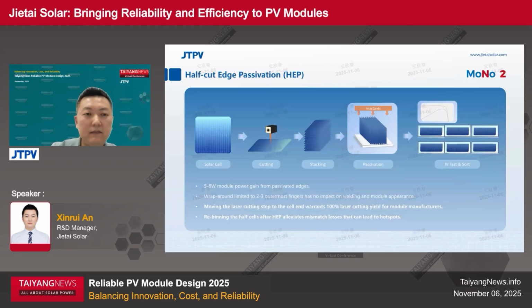And the other feature of Mono 2 cell, the half-cut edge passivation, HEP, not only enhances module power by 5 to 8 watts, but also contributes to more reliable modules. First, our wraparound is limited to the outermost 2 to 3 fingers, thus having no impact on welding or module aesthetics. And more importantly, moving the laser cutting step to the cell end effectively warrants 100% laser cutting yield for module suppliers. In addition, rebinning the half cells after HEP makes their characteristics more concentrated, and this can alleviate mismatch losses that can lead to hotspots.